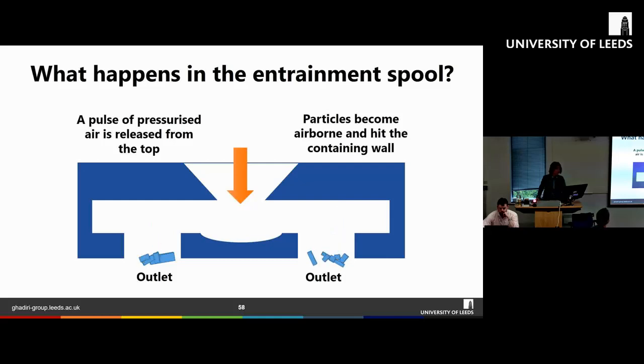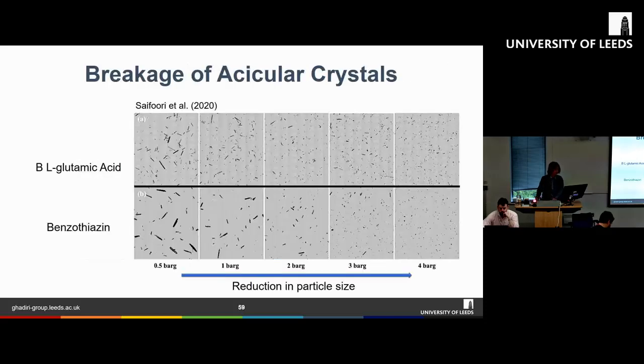So here, the sample well, we put the material here, and as a result of a pulse of air, the particle gets entrained and collides against the surface of this dispersion spool. They break and then they exit through this hole here, and then they settle down on a piece of glass slide for particle size analysis.